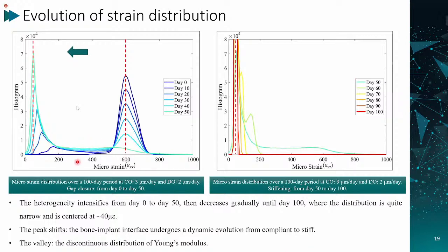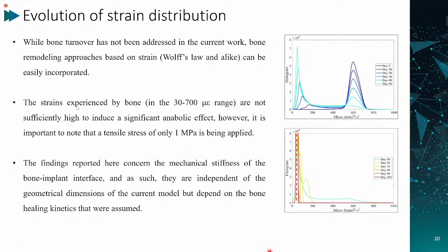And here, this value probably is due to the discontinuous distribution of Young's modulus we assigned in this model. So while bone turnover has not been addressed in the current work, bone remodeling approaches based on the strain, the famous Wolff's law, can be easily incorporated. The strain experienced by bone, deformation between 30 to 700 microstrain, is not sufficiently high to induce a significant anabolic effect.